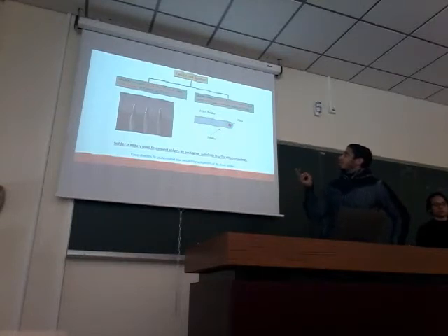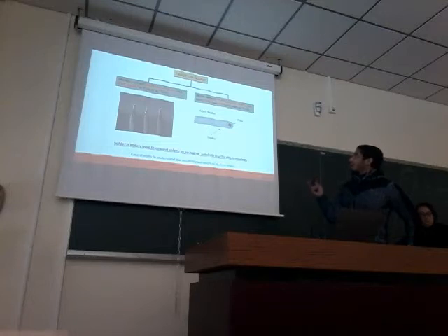There are two main types of lead-free solders that can be found. For instance, this number 1 is SAC 305, which contains different ratios of tin, silver, and copper, with a melting point of 217. The other type is SN100, which contains different ratios of tin, copper, and nickel, and melts at 228 degrees Celsius. And we can see this instrument here, which is used for soldering. It's used for connecting the chip to its backing substrate in flip chip technology.